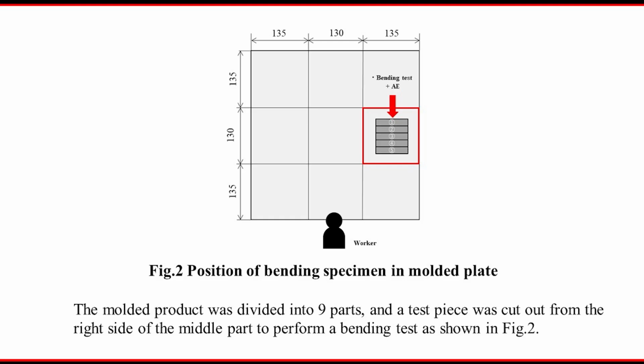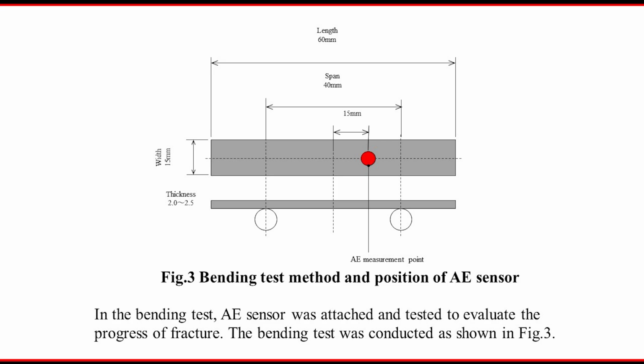This is a 400 millimeter square panel, and the bending specimen is cut out of this part. This is the bending specimen geometry, width and thickness, and this is a 3-point bending specimen. We use an acoustic emission technique with an AE sensor. Acoustic emission is used for understanding the fracture behavior. The fracture sound comes from inside the specimen when we apply the load, and the AE sensor can detect that fracture sound.